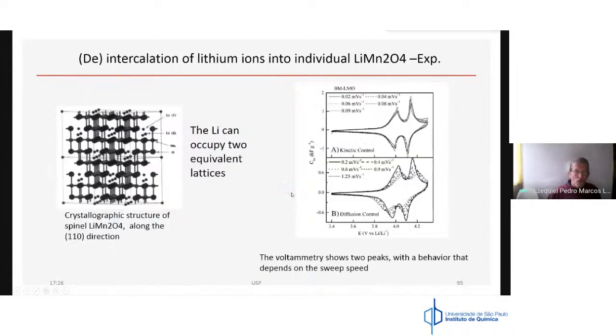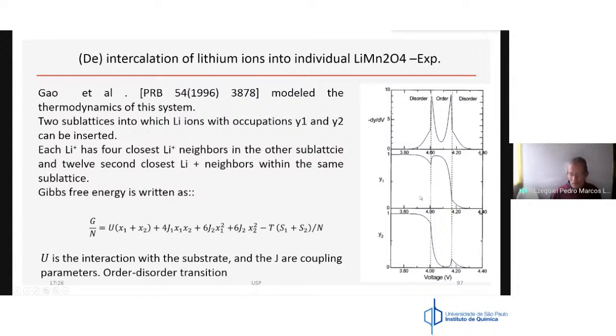So we decided to simulate the system by resolving the partial differential equations coming from the system. These are experimental voltammograms, and you can see the voltammograms are reversible at low sweep rate, and they change to be irreversible at higher sweep rate. There is some thermodynamic model for this system.